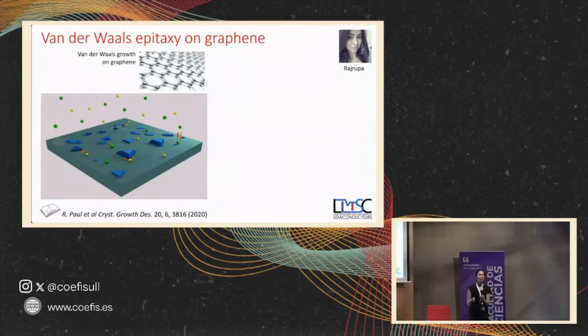There is no covalent bond with the substrate, which means that the atoms arrive, they have nowhere to stick. So this can be a problem, because they arrive, and they move around, but there is nothing to stick to, so they can evaporate again. But thank God, these materials are not perfect. The graphene is polycrystalline, so it has some grain boundaries and some point defects. So the material starts to solidify in these grain boundaries and then grows laterally.